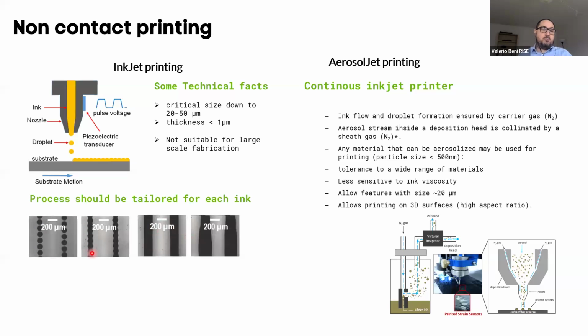This line starts to build up when you actually overlap the droplets more. But if you overlap the droplets a bit too much, or if the wetting properties of the inks are not adequate, you will actually have a spreading of that. So it's not a straightforward technology, and it requires some optimizations.